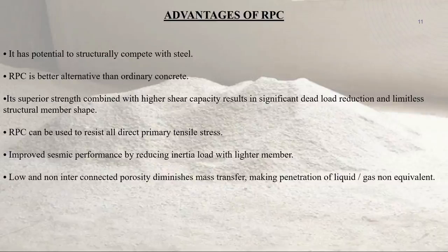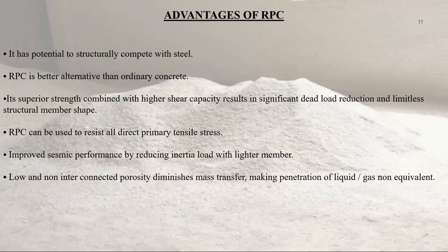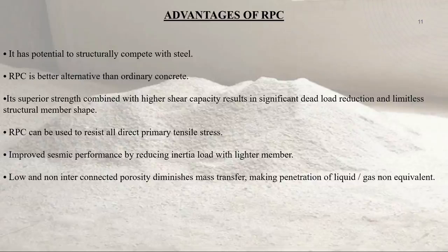Now we will discuss about the advantages of RPC. It has potential to structurally compete with steel, and is a better alternative than ordinary concrete. Its superior strength combined with higher shear capacity results in significant dead load reduction and limitless structural member shape. RPC can be used to resist all direct primary tensile stresses. It offers improved seismic performance by reducing inertia load with lighter members. Low and non-interconnected porosity diminishes mass transfer, making penetration of liquid and gas negligible.